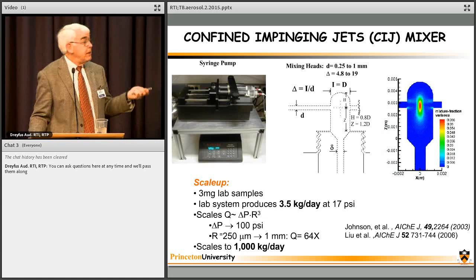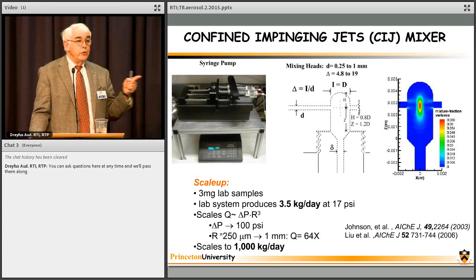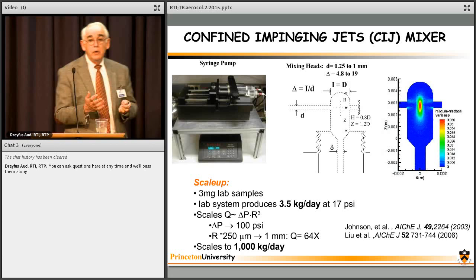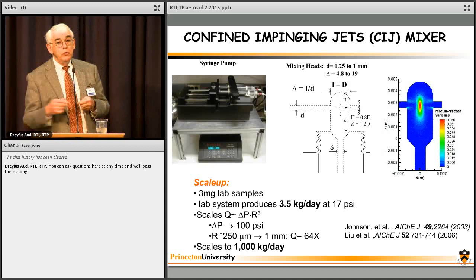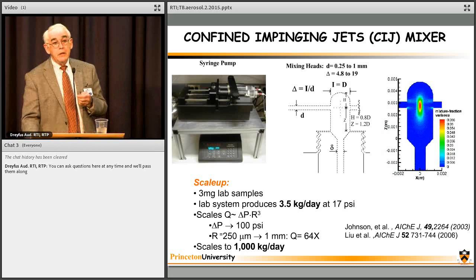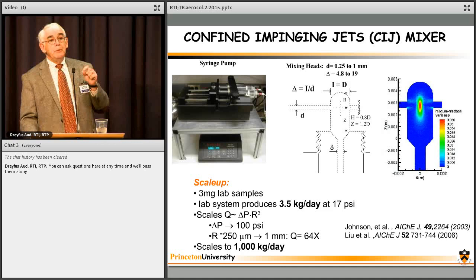Also, these microfluidics devices are really not scalable. But in this, we can make samples as small as about a milligram of material up to, if we run this continuously, 3.5 kilograms per day out of our lab. The fact that this is scalable because it's a continuous flow process is really important, and we can make the same materials at the milligram scale as at the kilogram scale. BASF uses this to make 1,400 kilograms per day of 100 nanometer beta-carotene salmon food. So the fact that BASF can make the beta-carotene, put it in this 100 nanometer form, cheaply enough to throw it in the ocean to feed salmon, says this is intrinsically a cheap process.